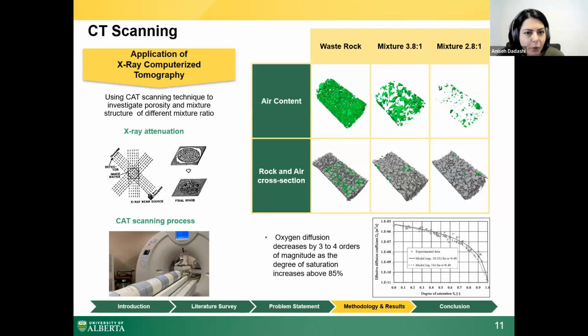To investigate the porosity and internal mixture structure, I used the CT scanning technique. As we all know, X-ray radiation experiences attenuation as it passes through the material. We can visualize and quantify the internal structure because of different attenuation between pores and solids. For the first round of experiment, I built the mixture ratios similar to my columns, and you can see they had different internal structure for different mixtures.